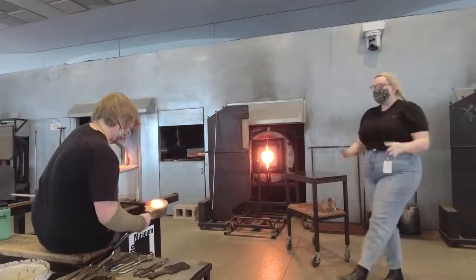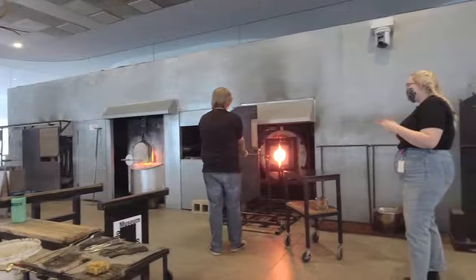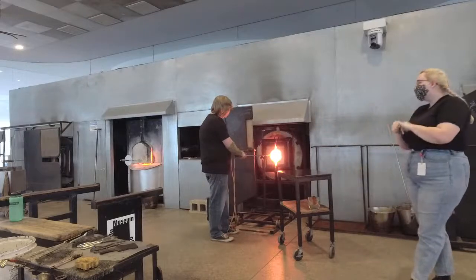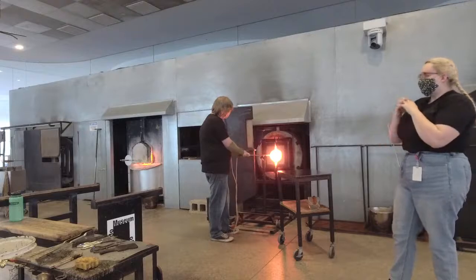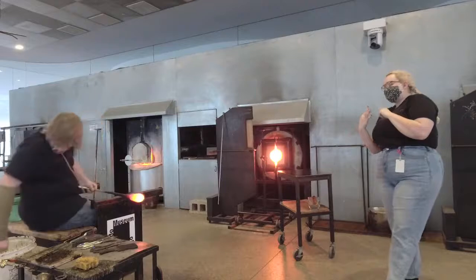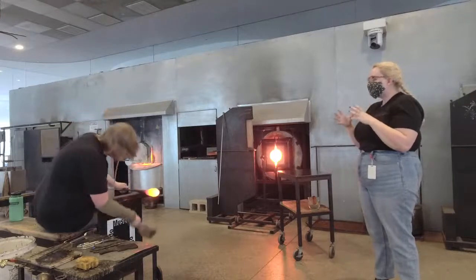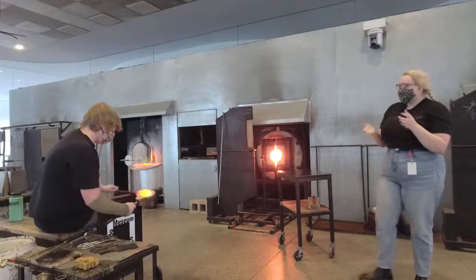Colin's using our wooden block tool. We have a very specialized tool set in here since that glass is so hot. Most tools you're familiar with in other mediums wouldn't work in here because they'd burn or catch on fire. Most of the tools on Colin's deck — his gaffer fence and tool deck — are made out of steel. Some are made out of a special type of wood, usually a fruit wood. In this case, everything Colin's working with is cherry. Cherry wood has a really tight grain pattern with not a lot of sap, so it water logs really nicely. Our block tool is using something we call the Leidenfrost effect — it's never actually making contact with the wood; it's really just creating a steam barrier. The steam is what's actually physically changing the shape of the glass. Glass naturally wants to be in a nice round shape.